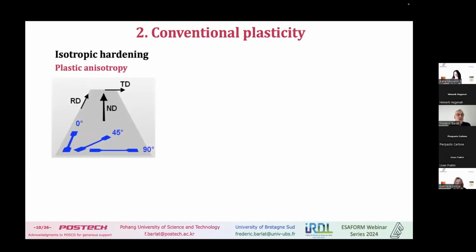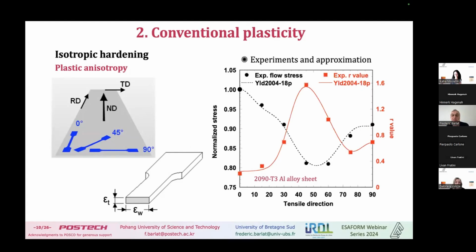And we can, using this, so I will show another example where we do tension in different directions, 0, 45, 90, but others also, 50 and so on. We can measure the flow stress from a tensile specimen, but also the ratio of the width to thickness strain, so the so-called R value in axial tension. And this is done on the aluminium 2090 T3. This is an aluminium lithium alloy, which was developed by Alcoa when I was working in Alcoa.